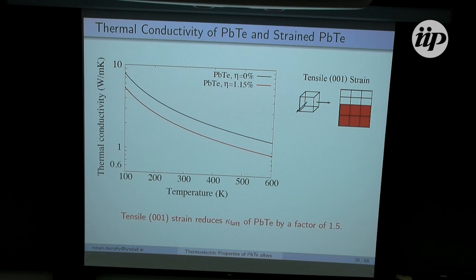So moving back to our results. So this is again the thermal conductivity, and lead telluride is in black, and strained lead telluride is in red. And we see we get quite a nice reduction by about a factor of 1.5 in this case. So again, I'll sound a bit like a broken record, but we've pushed lead telluride to the verge of the phase transition, increased that TO acoustic interaction, leading to this reduction in the thermal conductivity. So quite nicely demonstrates at least the principle of it.